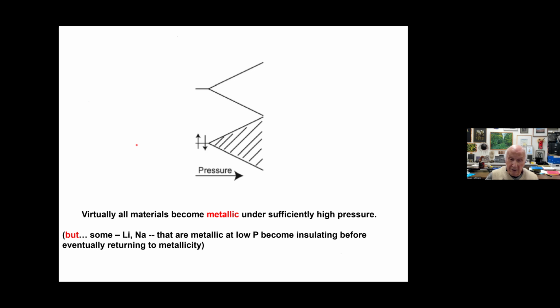There are some very interesting stories that have appeared in the last 20 years, and that is some materials like metallic lithium and sodium, which all of us know what they look like, especially sodium. These are metallic at low pressure, but as you compress them, they actually become insulating. But then eventually you compress them more, they return to metallicity again. To see metallic sodium, which every one of us has seen, to see it in a diamond anvil cell become transparent, because that's what it does, and insulating, but then return to metallicity, that is a very striking sight, which is one of the features of doing high pressure work.